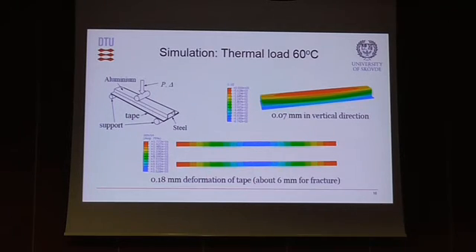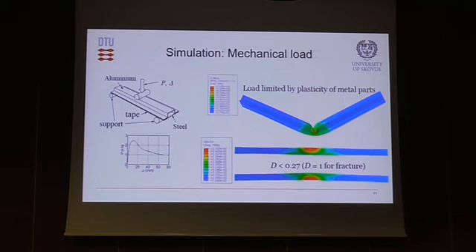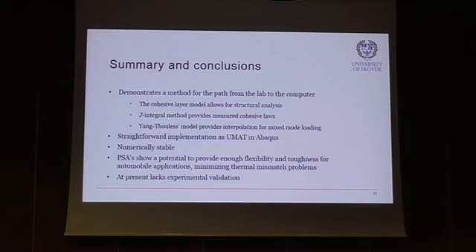The deformation of the tape is a maximum of 0.18 millimeter, and it's shear, of course, in the tape. For this tape, you need 6 millimeter for fracture. So it's all elastic. The mechanical load is different. Now we put a prescribed displacement at the center, and what we find is that the load is limited by plasticity of the metals, no sign of fracture in the tape. By this way, it seems that tapes could be useful for this type of application. Of course, there is much more work to be done before you can convince people about this.